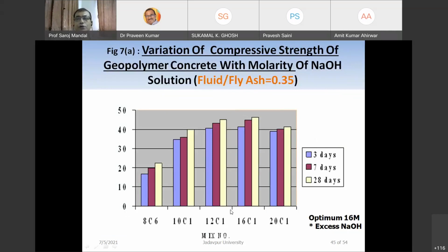So if we change the molar concentration, keeping others the same, see here, the fluid to fly ash content remains the same, but we are increasing the molarity. So this is the mix number. Basically, all these have different molarity. This is 8M, this is 10M, 12 and 16, right? So what we get here is, if we increase the molarity, the strength increases in all cases, at 3 days, 7 days and 28 days.